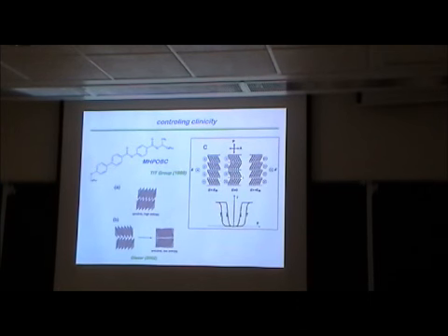There are also phases that are anticlinic, where you have opposite tilts in opposite layers. This comes about in this case because in this molecule you have a tail which tends not to be straight. At this bond with the core, it bends to be parallel to the layers. So this tail suppresses out-of-layer fluctuations, so it keeps the molecules in the layers.